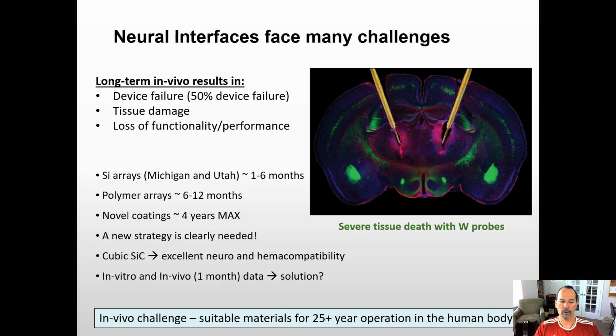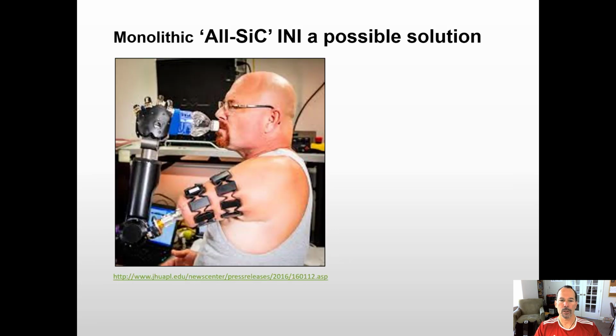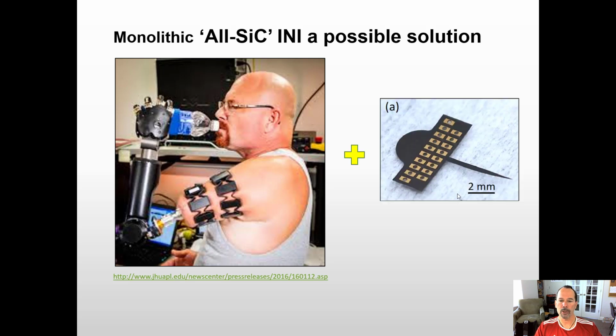So our in vivo challenge that I've put down in front of my students is the following. We want to demonstrate 25 plus year operation in the human body of silicon carbide implants. And that's when we start to really take advantage of the long-term, robust, corrosion-resistant properties of silicon carbide compared to other methods. So here again is Johnny, and again using EMG sensors to basically pick up signals from the upper arm and then wirelessly send them to both the elbow and the hand. And we believe one solution to this would be such an all silicon carbide, perfectly monolithic silicon carbide implant.